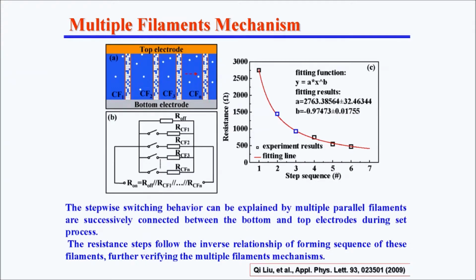To explain this phenomenon, we propose a model for explaining the multiple filament switching mechanism. Several filaments are connected in parallel successively. Based on this model, we can match the experiment results very well. Actually, this model, when published in APL in 2009, is widely used by this society to explain this step-like, multiple filaments phenomenon.